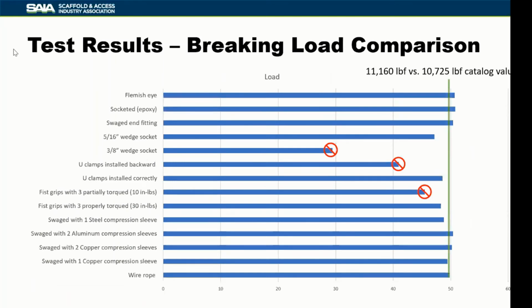If we summarize all of the results in terms of breaking load, what we see is the Flemish eye, the socketed or Spelter socket, the swedged end fitting, going down to the 2 aluminum compression sleeves, the 2 copper compression sleeves, and just marginally 1 copper compression sleeve. All of those basically come up to the catalog strength of the wire rope itself, at 10,725 pounds.